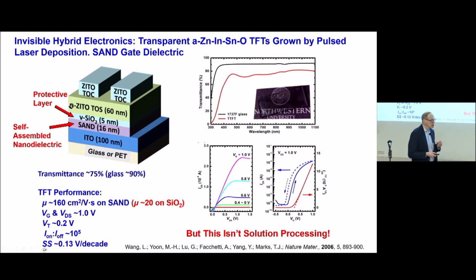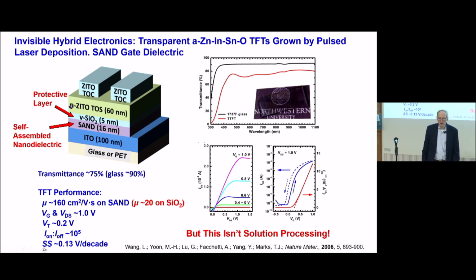Remember we were talking about amorphous silicon having a mobility of 0.5. This is 160. On silicon dioxide it's about 20, but on this special gate dielectric we've developed, it's 160. I first showed this at a conference, and Hosono jumped up and started pounding the table. He gets very, very emotional about these things. He didn't believe it, and we convinced him that it's real. And this is just showing some of the data, the transfer plot, and minimum hysteresis.